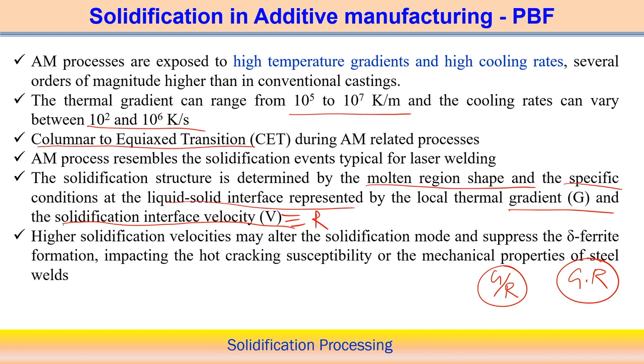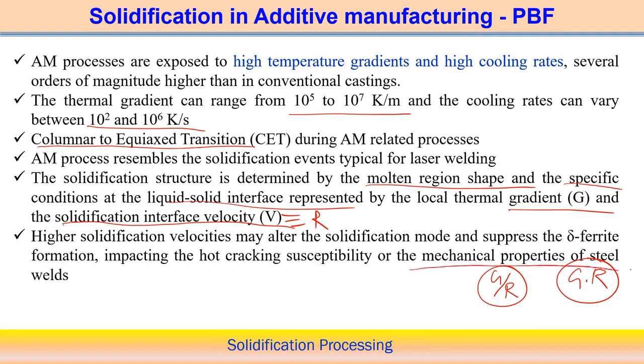When solidification velocity is very high, it suppresses delta ferrite formation. The composition of delta ferrite contains a very low percentage of carbon in steel. If high welding speed suppresses delta ferrite formation, it promotes cracking susceptibility and can influence the mechanical properties of the steel weld.